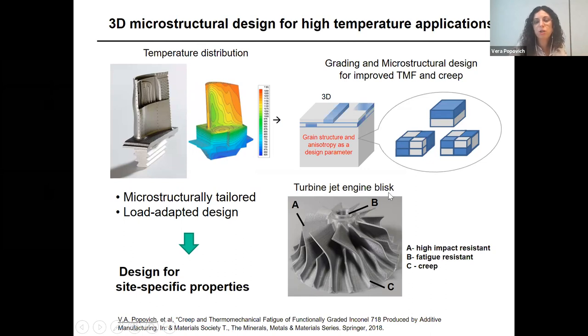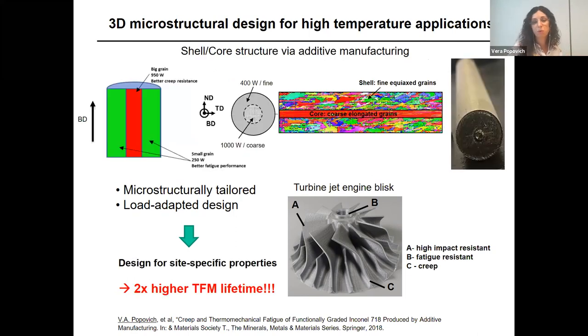So if you take a turbine jet engine blisk, you can have areas that would require more high impact resistance, high fatigue resistance, or high creep resistance. So with additive technologies, you can use this as a puzzle. You can put different microstructures and different properties together as a puzzle to tackle what we call site-specific properties. And that's exactly what we also did with our components. We developed this kind of shell-core structure, so that we have a shell and envelope surrounded by fine grains, shown here, while the core has single elongated grains along the 001 direction.